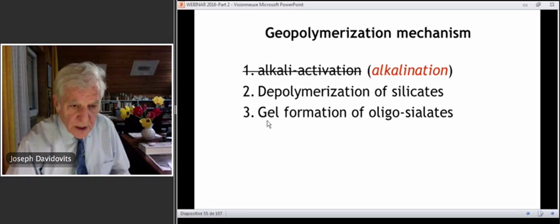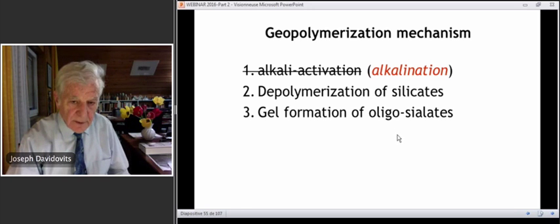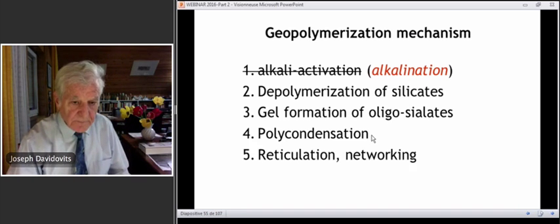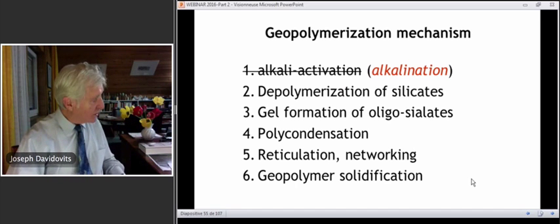Then we have a formation of a gel of smaller molecules, oligo-sialates. It is a gel because they are in water medium and they are not polymerized. Then we start the polycondensation. That is, the molecules are becoming bigger and bigger: reticulation, networking, and geopolymer solidification.